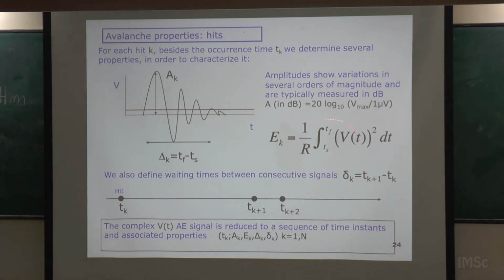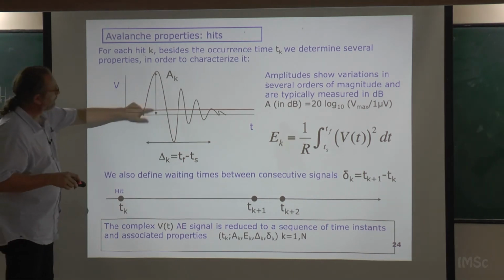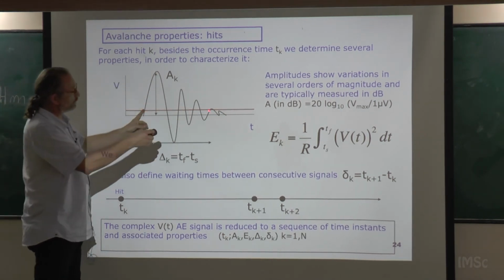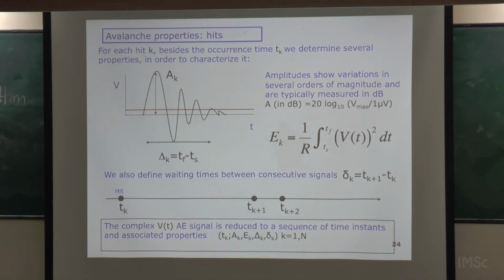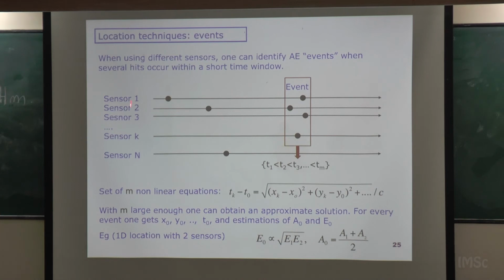And by integrating, you can measure the energy, the amplitude of the hit, the duration of the hit, etc. So at the end, what you obtain with this technique is a series of events, of hits. Each one occurred at a given moment, and each one has this energy, this amplitude, and this duration. And this is what we call a catalog. A catalog of acoustic emission data is just a list of the hits, and this is typically obtained when driving the system very, very slowly. You start in one phase, you drive very slowly, you go to the new phase, and then you record this sequence of information, okay?